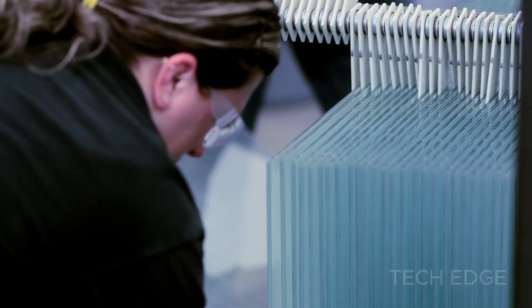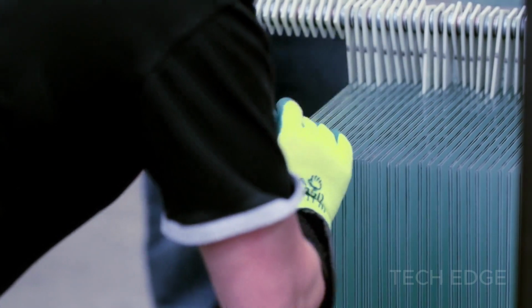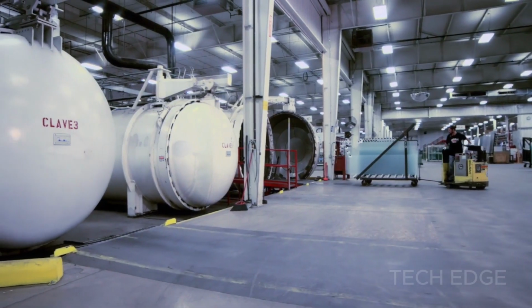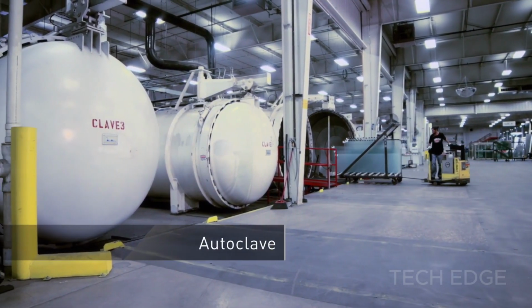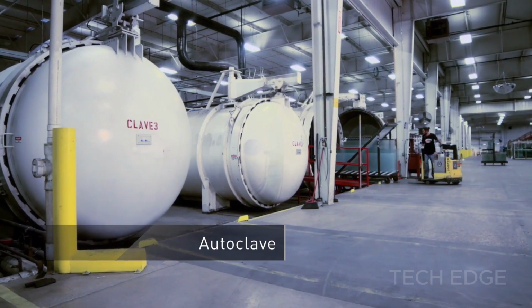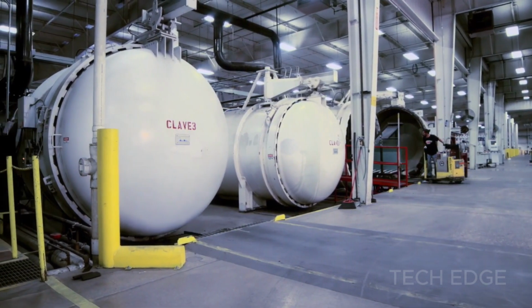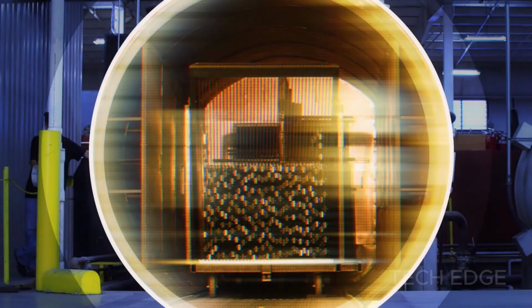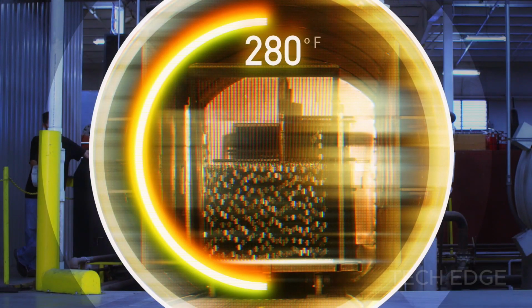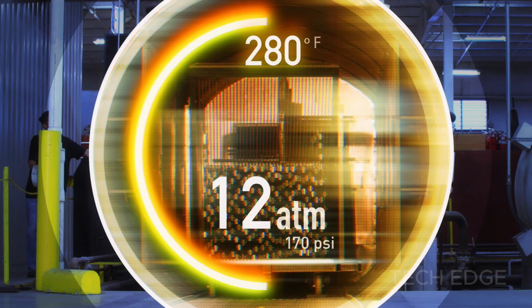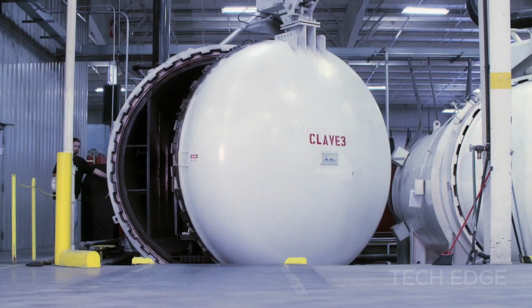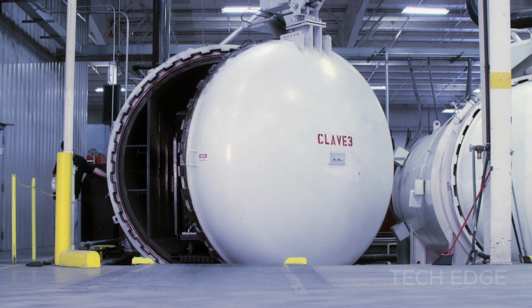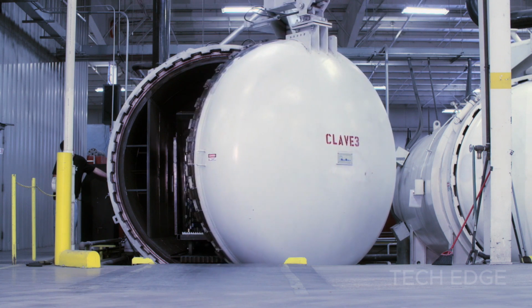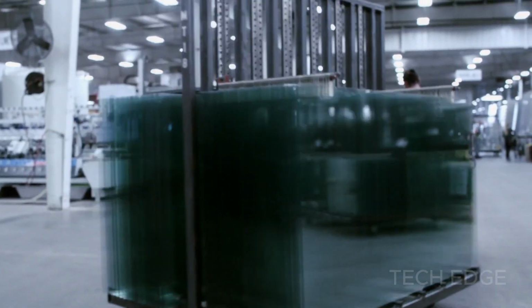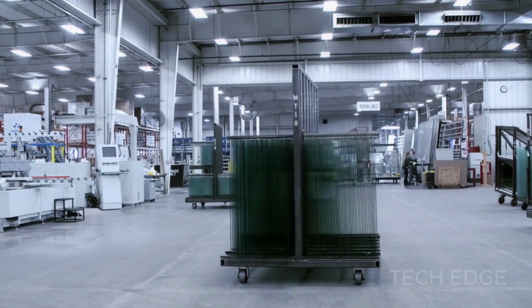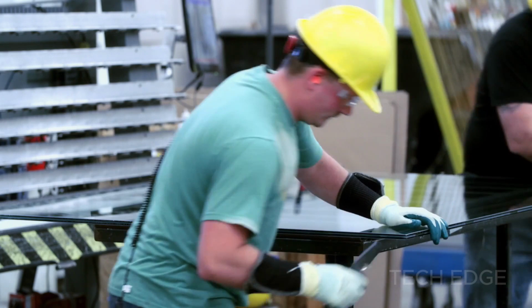The second step involves the autoclave process, where the laminated glass is subjected to intense heat and pressure in a chamber. The temperature reaches 280 degrees Fahrenheit, and the pressure exceeds 12 times atmospheric pressure for a period of 2 hours. This process removes residual moisture and ensures the interlayer adhesively bonds to the glass, resulting in a clear product. Finally, technicians perform a precision trim of any remaining interlayer and move the panes to the online glass inspection conveyor for quality verification.